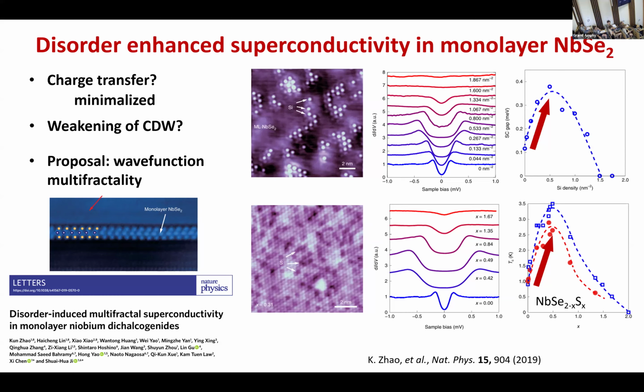So then they started to investigate this thing and realized that silicon can actually do something to the niobium diselenide. In the STM measurement, they show that by just doping some silicon on the surface, just evaporating some silicon on the surface, then with the coverage of silicon increasing, the superconducting gap first increases and then decreases. And silicon does not donate any electrons or holes to the system. It does just increase the disorder. And similar things happen for sulfur.